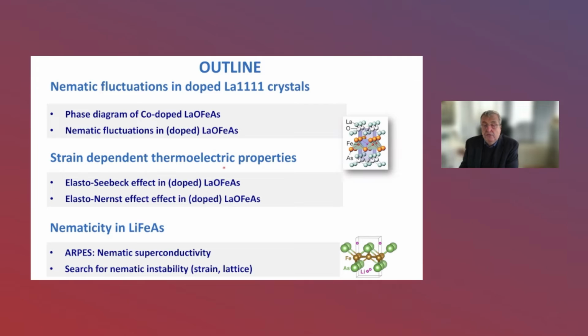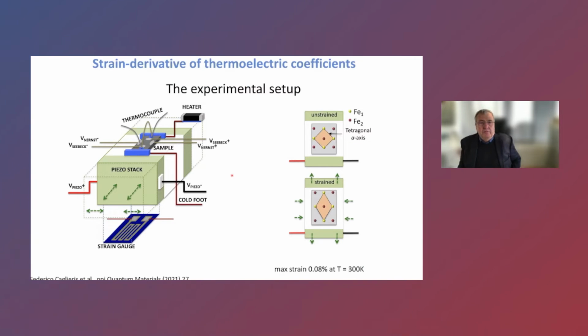and this is dealing with the strain-dependent thermoelectric properties. So you can measure not only resistivity under strain, you can also measure more complicated transport properties under strain. And what we developed here is a technique to measure thermoelectric coefficients as a function of strain. So again, starting point is this piezo stack. We take the single crystals, put it on top of that. Now we apply a thermal gradient.